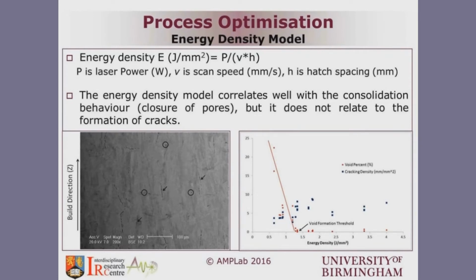For quite some time, people have been using the energy density model, which is basically an equation that lumps together many of the process parameters in a single figure of merit that indicates how much heat, how much energy density, is being given to the material. That equation is the power over the scan speed V times the hatch or overlap spacing, and in some other versions, power divided by scan speed times hatch spacing times layer thickness. This equation was used to correlate the heat input with the defects that form in the process.